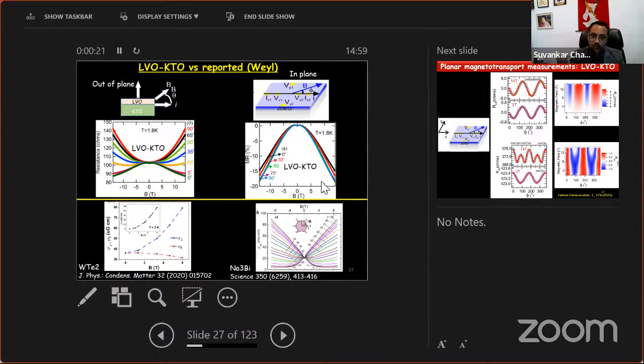Yes. Sure. I completely agree with this. That is why I want to emphasize. See, although from the out of plane part, it looks like it has a positive to negative magnetoresistance transformation, if you go to 5 to 25 degrees, it goes away. But in case of in plane magnetoresistance, it never vanishes. It's always negative magnetoresistance, which is a complete contrast to Weyl, and the idea of Weyl, because if you make a little deviation of phi, even in the in plane, it should go from negative to positive. So really it is questionable whether we are seeing Weyl or not.